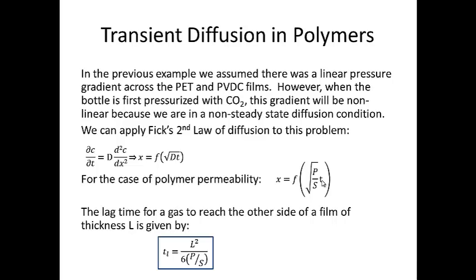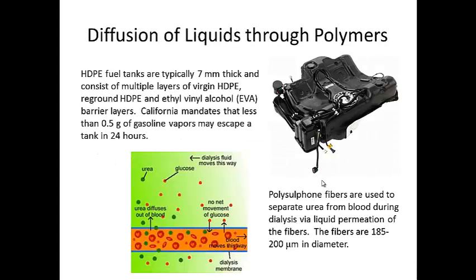If we solve this basic equation, we determine what is called the lag time for a gas to reach the other side of a film of thickness L, assuming we have a homogeneous film. The lag time T sub L is equal to the length squared divided by 6 times the ratio of the permeability to the sorption. So if we have a very high sorption, we tend to have a large lag time. In addition, we can greatly increase the lag time by changing the thickness of the film, and we can also increase the lag time by decreasing the permeability of the film.